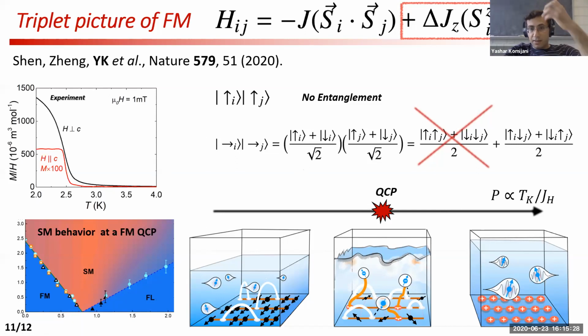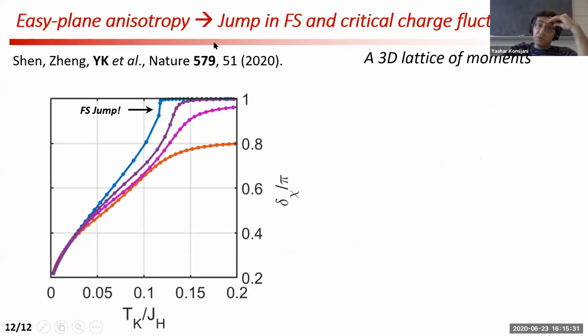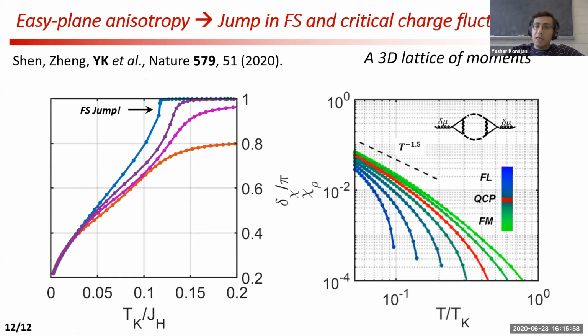And this is not just cartoons. We can go back to your Schwinger boson solver and add some easy plane anisotropy to the system, and we see that the phase shift will not evolve continuously anymore, but it will show a small jump, and the size of the jump is related to the amount of the anisotropy that is included. And so this is high temperature, and then blue would be the low temperature. And associated with that, there will be some critical charge fluctuations. So in this case, it has a different exponent, but it exists at the quantum critical point.